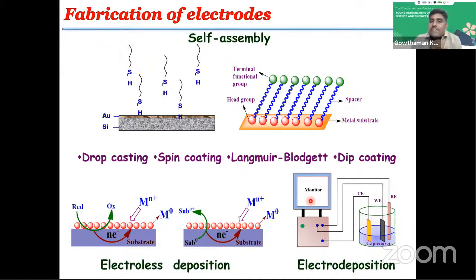And here, the first one is self-assembly using a linker. Generally, gold nanoparticles are attached on the electrode surface via a thiol linker. With a thiol linker, the SH Au-S bond, you know that Au-S bond very well. It is a familiar one. So if you want to attach gold nanoparticles on the electrode surface, we can use the thiol linker.